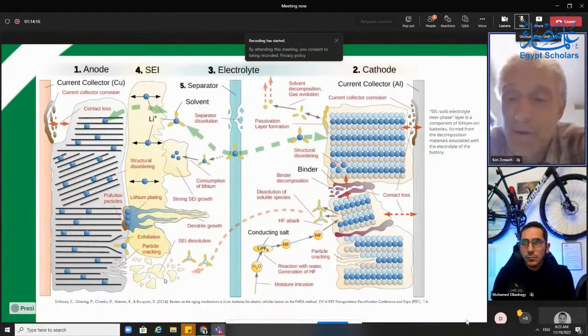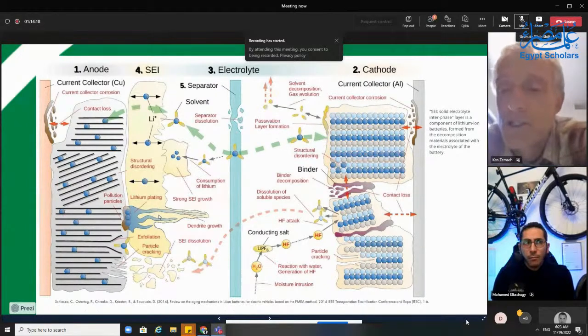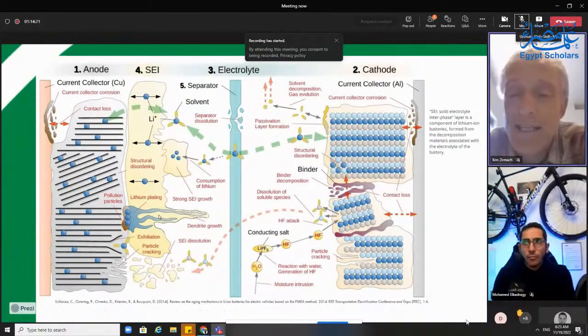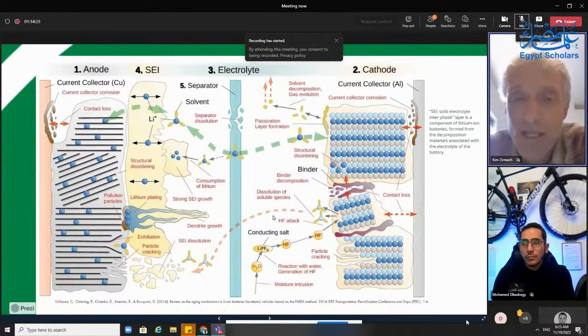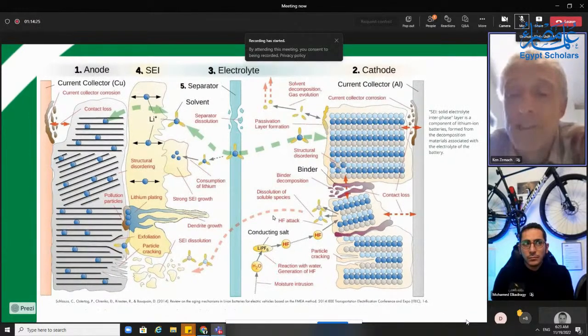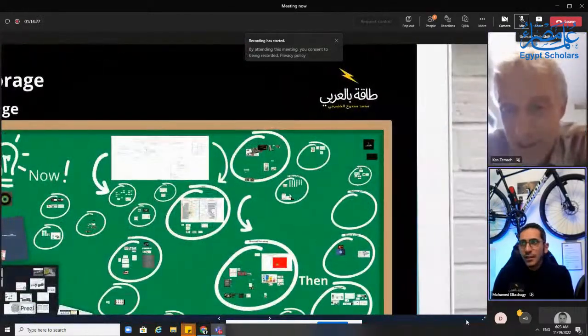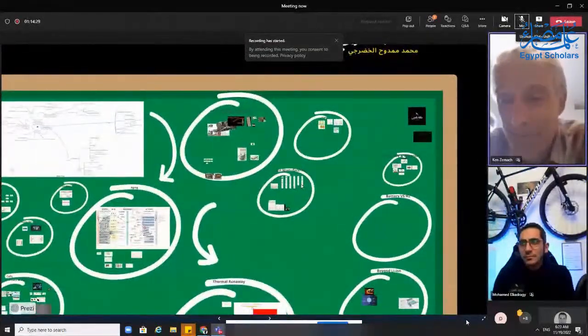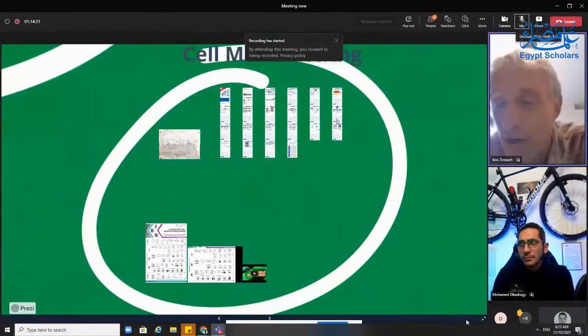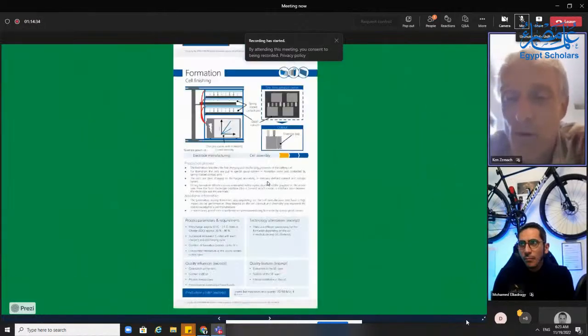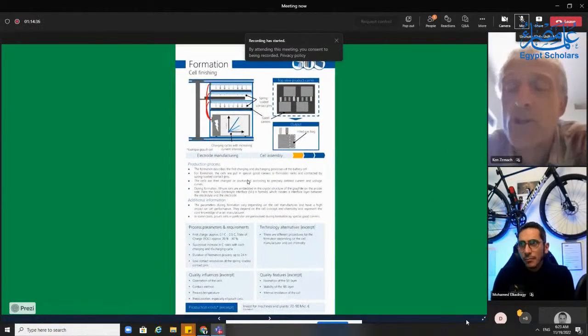And the problem is, if you fill your cell, seal it up, and then send it directly into formation and aging, that gas will blow up your cell like a balloon. So you have a degassing phase, which is sort of this pre-charge plus putting it under vacuum to pull the majority of the gas off.